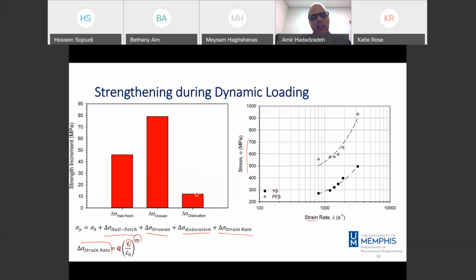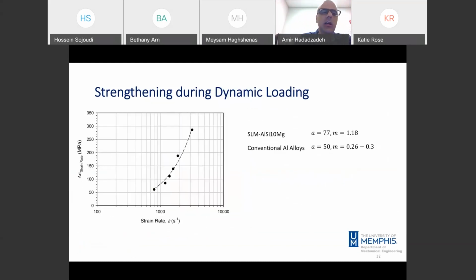If we subtract these three components, the Hall-Petch, the Orowan, and dislocation, from the values here, we can now end up with the increment because of the strain rate. Okay? And by doing a curve fitting, the values for SLM AlSi10Mg are shown here. A is 77 and M is 1.18. If we compare it to conventional aluminum alloys from literature, you see different values, a significant difference between these two values, A and M. Or if I plot a graph for the conventional alloys on this graph, we'll have something like this. There is a significant difference between two types of materials,